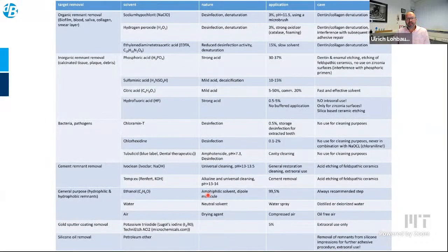So the one thing I wish to share is that cleaning of the fracture surface is of key importance. If you don't clean a surface, you don't see anything on a surface, and it very much depends on the material you have. A glass ceramic material, for example, is etchable with hydrofluoric acid, so you modify the structure. This is certainly not recommended for silicate-based ceramic materials, but is certainly harmless, at least in a low concentration, on a zirconia surface. It's the other way around with phosphoric acid, for example: the phosphoric group in the phosphoric acid reacts with the zirconia surface and contaminates the surface, but on the other side, you can use it for cleaning of silica-based ceramics.